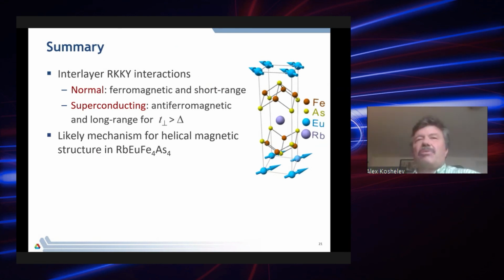So in conclusion, we investigated interlayer interaction: in the normal state, it is ferromagnetic and short range; in the superconducting state, it is antiferromagnetic and may be long range if the hopping integral exceeds the gap. And I believe this is the most likely mechanism for the helical magnetic structure in this material. Thank you very much.